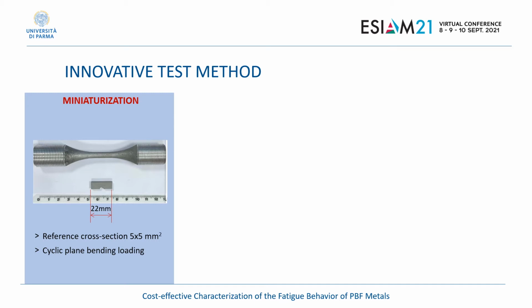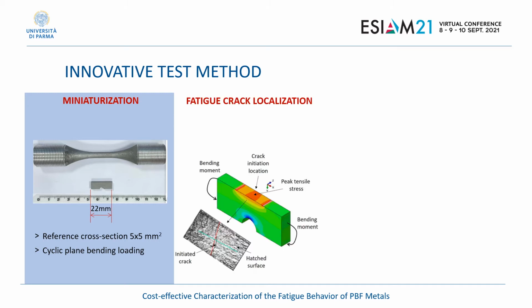We answered those needs with an innovative test method that's shown here, and it's based on the concept of miniaturization. We see in the picture a mini specimen, 22 mm long, compared to the standard push-pull testing specimen. This mini specimen is loaded cyclically in bending according to the scheme shown here. In this way, we can control the crack initiation location and therefore the fatigue behavior as a smooth surface condition.